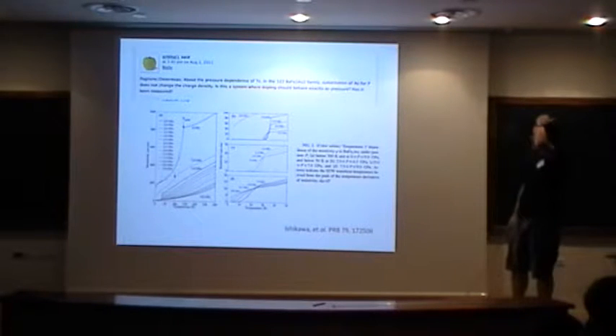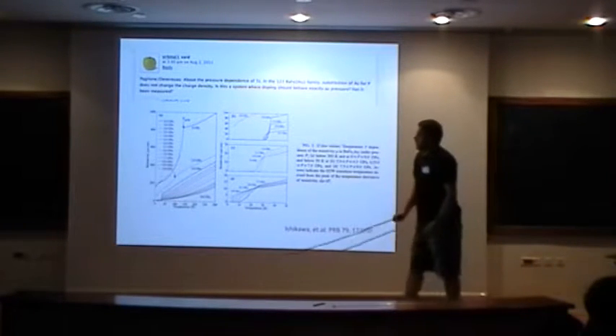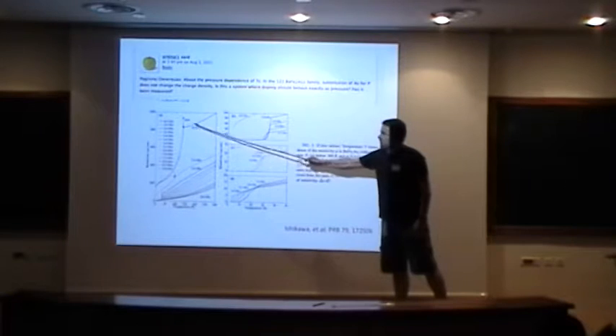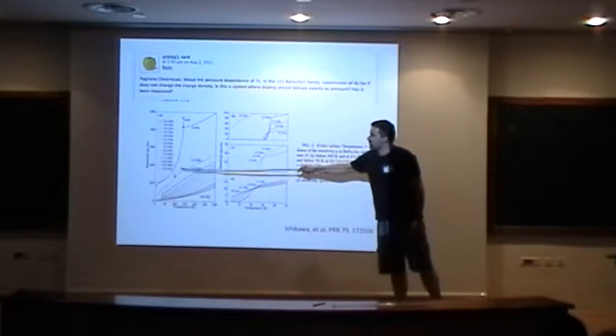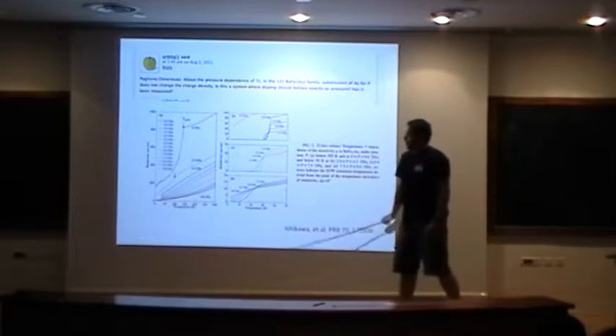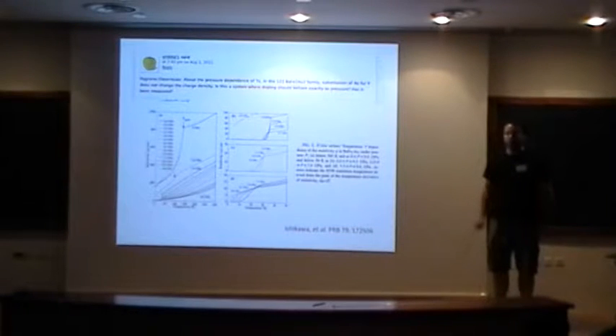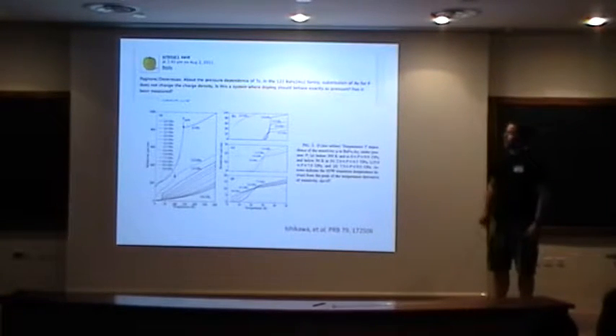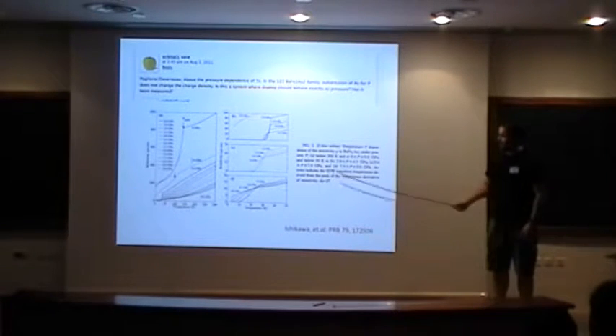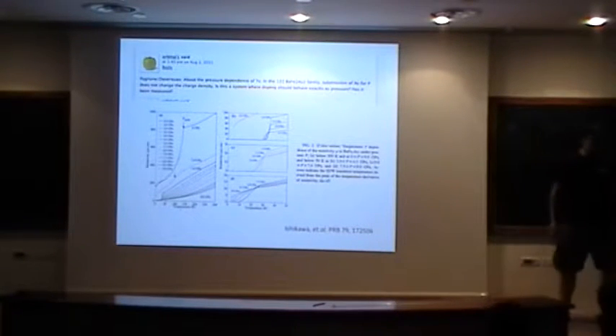And also, at around the optimal doping, they see that the spin density wave transition in the resistivity goes away. So this also follows the behavior by doping. So obviously, yes, it's possible, and yes, it has been measured.